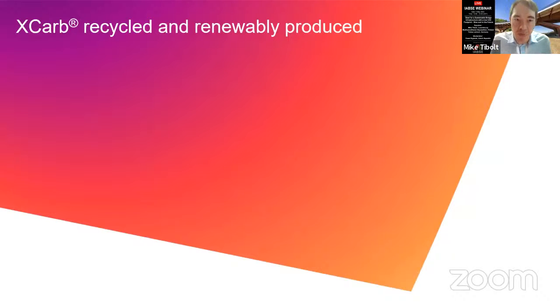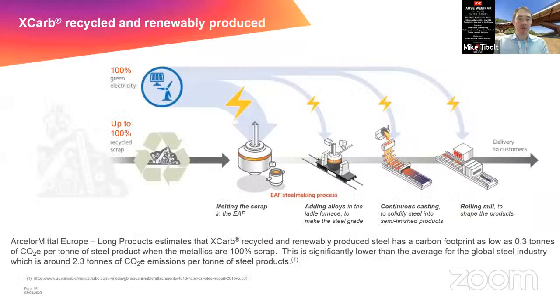So starting first of all with the X-Carb recycled and renewably produced. X-Carb recycled and renewably produced is the brand which covers all the steel which is produced in the secondary production route, so meaning by electric arc furnace. By using 100% of green electricity, purchased via guarantees of origin in the European system, and to feed with this energy the whole production line of steel, and to use up to 100% scrap. And by doing so, we can reduce the carbon footprint of the product down to about 0.3 tons of CO2 equivalent per ton of steel product. And this is significantly lower than the current average of steel production, which lies at 2.3 tons of CO2 emissions.